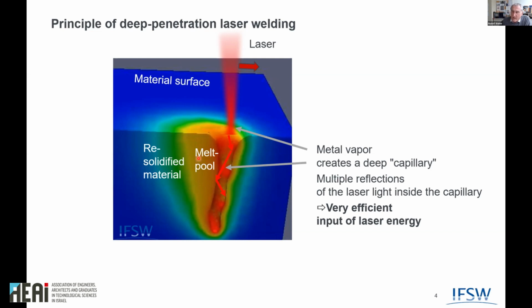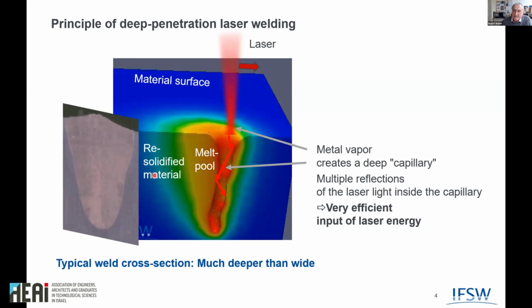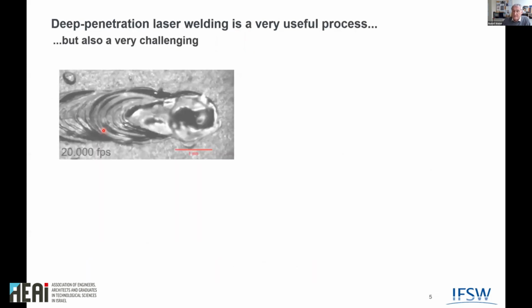We have some melt pool where the material is molten, and then after a certain time or certain space during the movement, it resolidifies, and what we get is a weld seam, of course, which might look like this. This is a typical cross section of a nice weld. This is the surface. That's where the material was molten. And what you can easily do with laser is that it's much deeper than wide. And this can be done very fast.